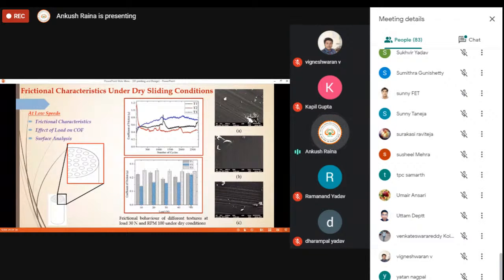From these figures, you can see that texture T2 has a lower coefficient of friction in comparison to texture T1 and texture T3. So these are the results. Basically, we try to find out the optimum texture size or the optimum texture density, which will give us a minimum coefficient of friction, which is possible with texture T2. Because the size of texture T1 is less, the size of texture T2 is more, whereas the size of texture T3 is much more.